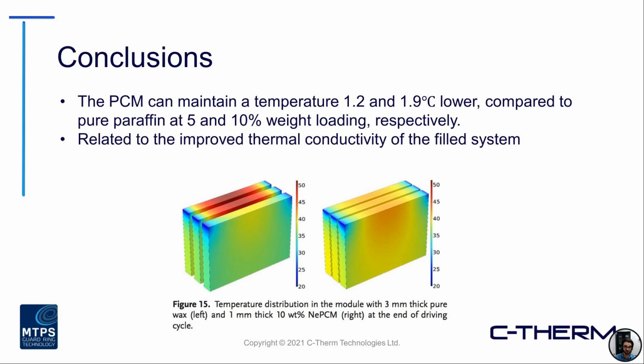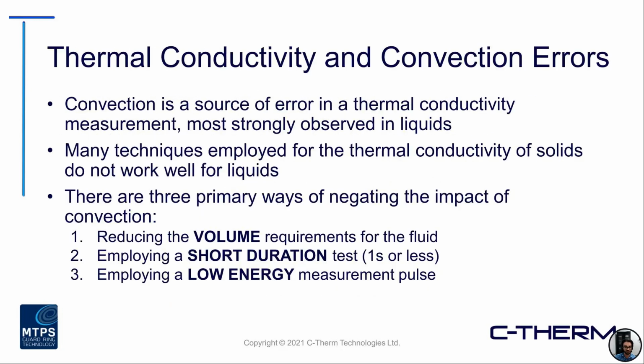So ultimately what they were able to conclude, taking this data and going through some simulation studies, is the PCM can maintain a temperature about 1.2 and 1.9 degrees lower compared to the control at the 5 and 10% weight loading, respectively. Ultimately, this all comes back to the improved thermal conductivity of the filled system. So really just demonstrating in a very simple sense here that the effective thermal conductivity can have a very large impact on the overall temperature that will be imparted into your system.